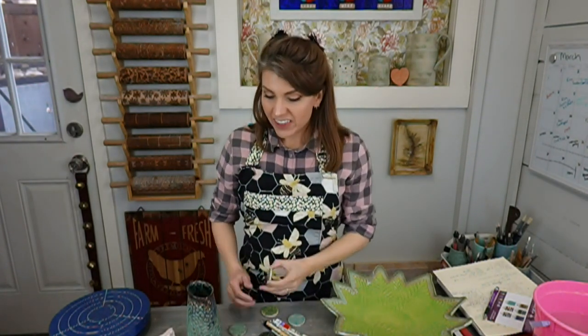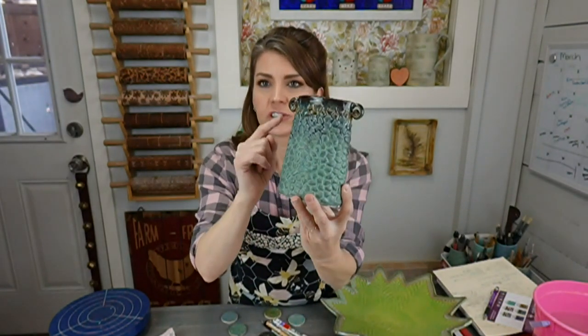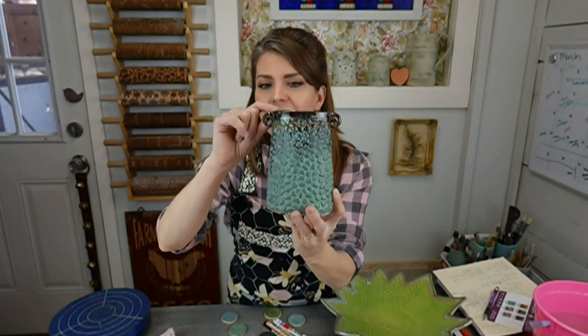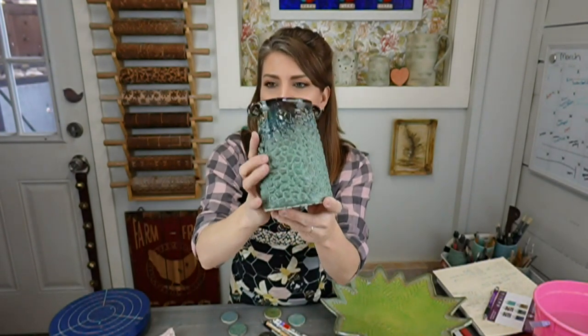So I see some people, Jeannie has just bought these colors. They are nice. And I'm going to tell you a secret on this right here. What you do is you put your river rock on first, and you start about a third of the way down, and you glaze from river rock a third of the way down up to the top, 3 coats. Then you put your blue stone on top of the river rock, stopping about a half inch from the very top, so you have that rim that's that nice dark brown, and then you have the overlap, and then you have the blue stone, so you get that gradation happening. And then I'll flip it around, you can see both sides.